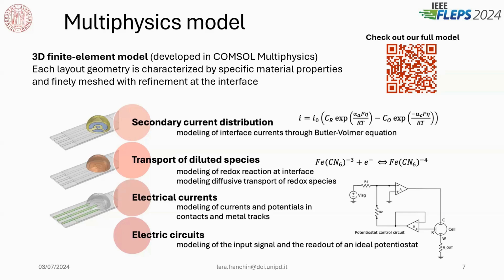The first one models the interface current through the Butler-Volmer equation. Then we model the redox reaction at the interface through the Nernst equation, and the diffusive transport through Fick's laws, of course. And then the electrical currents models the currents and the potential in the metal contacts and the tracks. And finally, we have designed an equivalent circuit of an ideal potentiostat to model how the input signal and the readout are made. And if you want more detail about this model, you can check our final paper about it here.